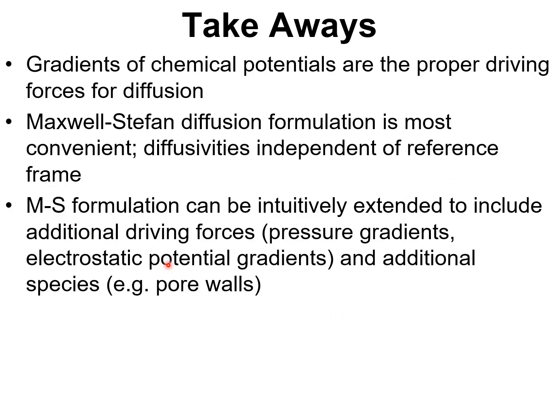The Maxwell-Stefan formulation can be intuitively extended to include additional driving forces, for example, pressure gradients, electrostatic potential gradients, and also additional species in the mixture. The pore walls of a porous medium, such as zeolites or metal organic frameworks, can be considered to be a pseudo-species in the mixture. Indeed, the Maxwell-Stefan formulation is the most convenient one to describe diffusion inside zeolites and MOFs.